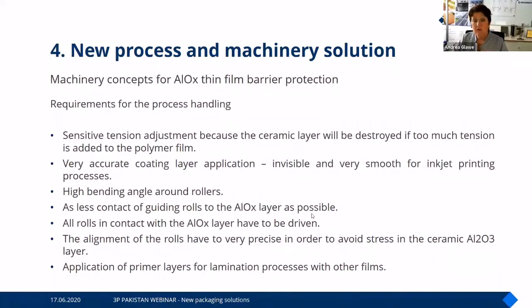We really look to avoid contact to guiding rollers, and as soon as a guiding roller comes in contact with the AlOx, which you can't avoid, this roller should be driven. It's also very important to have a very perfect alignment of the material in the machine to avoid stress on the ceramic layer. We are looking into a very proper tension control in the machine, and this is very important to really keep the very good functionality of the AlOx layer in a proper way.